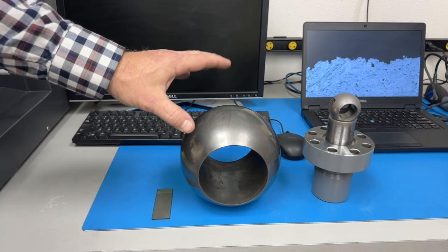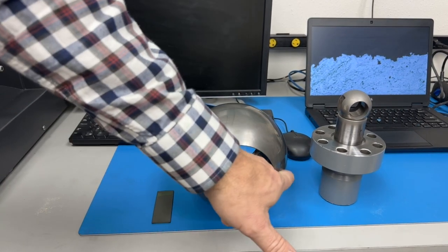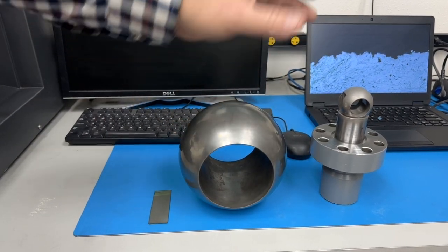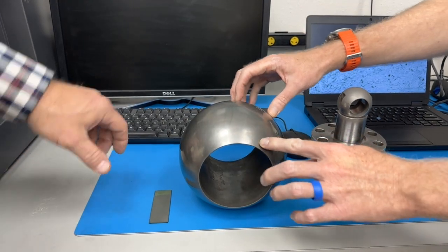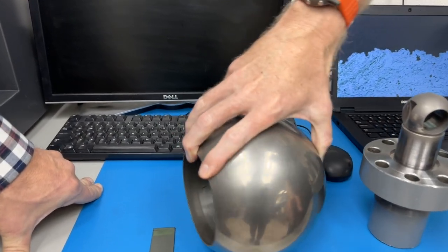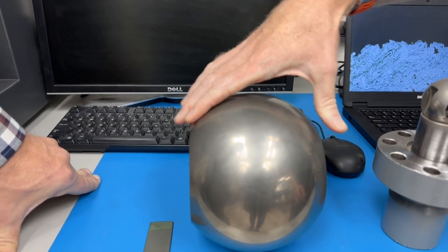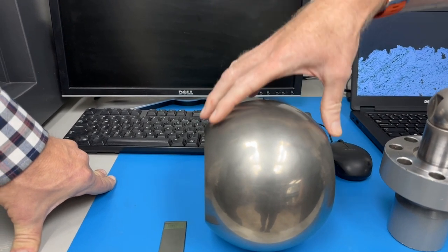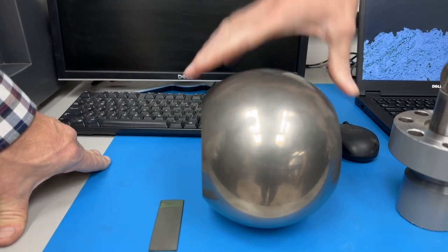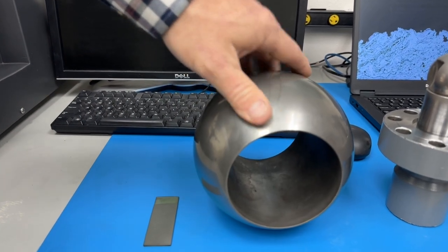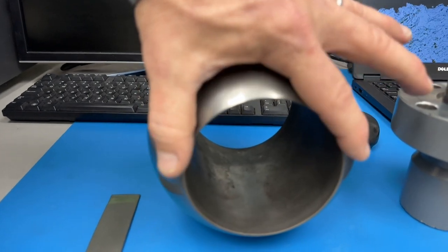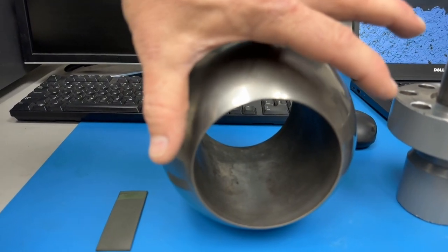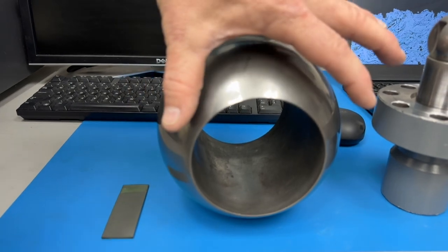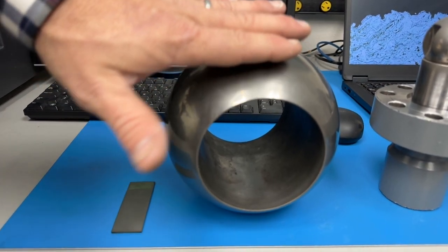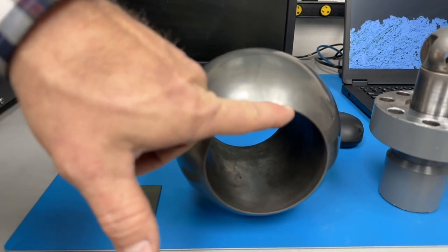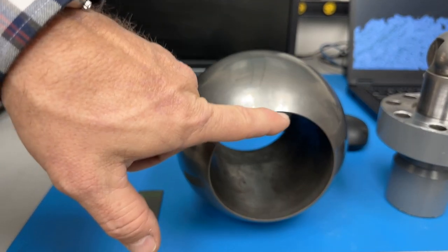The areas that you're most concerned about are leak paths in the sealing area near the bore or where it meets the seat. Yeah, so that would be here where it touches the seat, or potentially here where it's in the fully closed position. These are the spots where it needs to be as perfect as possible. That's correct. A lot of times what we've found is the way that the balls and seats are designed, if they aren't designed properly, and I won't tell you how, and the coating isn't applied properly at these edges, it will leave a leak path kind of like a scratch would here, which will allow it to delaminate.